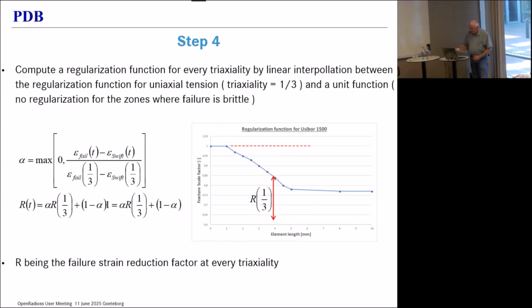Well, with that, we're now going to generate a regularization function for every triaxiality. And we do that by linear interpolation. So for every triaxiality, we compute failure strain minus swift strain, and we divide that by failure strain minus swift strain for a triaxiality of 1/3. We cut the value at 0. That gives us a factor alpha.